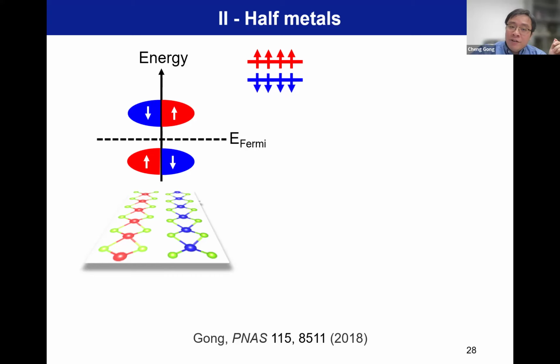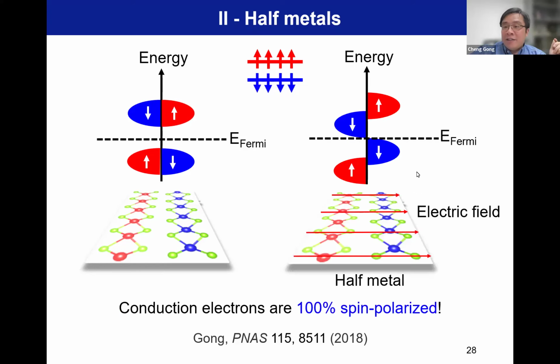Now, if you apply an electric field across these two layers, you can see the electrostatic energy on the two layers is different. So they will push down one layer's energy band and lift up the energy band of the other layer relatively. So finally, you will have one band merge, the other band remaining open. So now the Fermi level crosses one spin polarized band, you have 100% spin polarized carriers for transport. And then you have another spin polarized band as an insulator. So basically you can see here, it's still anti-ferromagnet, but spin up, spin down bands are split. So you have a half metal.